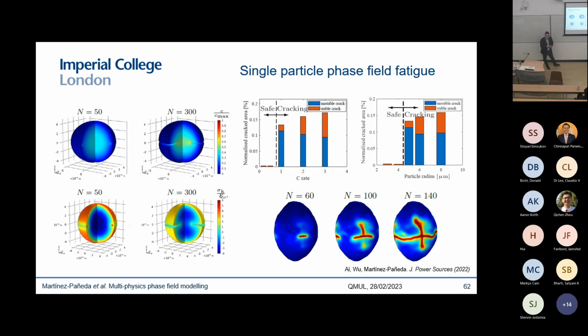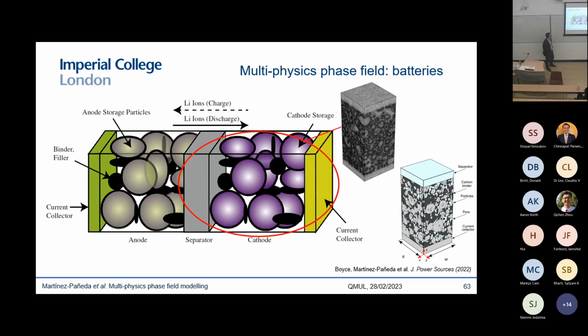At the end of the day, again, you have a virtual platform whereby you can change the loading conditions, the material properties, the particle radius, anything that you want, and test it and see what is the impact on the fatigue behavior. For example, you can see here that we can determine the particle radius and the C-rate thresholds below which we will not see any fatigue cracking for 300 cycles, which is a sensible estimate for these batteries in the context of electric vehicles.